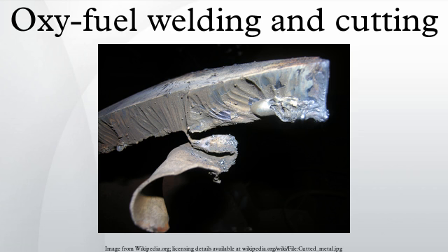Acetylene. Acetylene is the primary fuel for oxy-fuel welding and is the fuel of choice for repair work and general cutting and welding. Acetylene gas is shipped in special cylinders designed to keep the gas dissolved. The cylinders are packed with porous materials such as asbestos, then filled to around 50% capacity with acetone, as acetylene is acetone-soluble. This method is necessary because above 207 kPa acetylene is unstable and may explode. There is about 1700 kPa pressure in the tank when full.